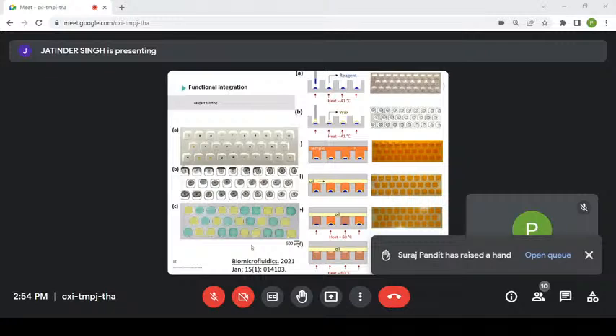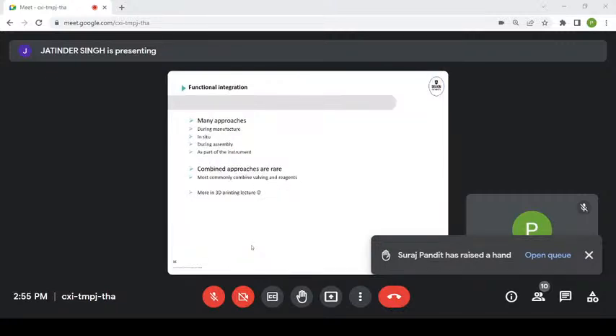And the main reason people like drying in of reagents rather than storing them liquid is that they can be stored at room temperature, and we don't get a lot of problems with cold chain storage that we have for a lot of thermolabile enzymes, and we don't get any problem of growth either. So dry reagents are a much more stable way of integrating reagents than when we try to have the liquid reagents in the blister packs.